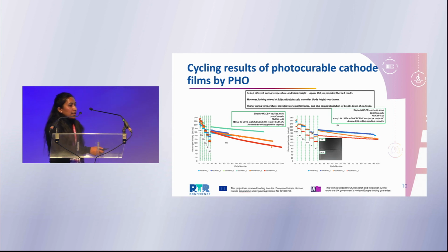So they are doing parallel testing of NMC with commercial NMC, to see if they can photocure it or not, and they have already tested with liquid electrolytes to make the validation, and further it will be tested on the solid-state electrolytes. Here the partners are focused on optimizing different temperatures and blade heights for the UV curable photopolymerizable cathode materials, and they have tested rate capability at different C rates, and they could achieve really good capacity, almost up to commercial electrodes, even after the photocuring and addition of different materials. So it's going in a good direction, I would say, compared to other NMC materials with other kinds of solid-state electrolytes. Given the challenges in this particular project, it's still going really well in terms of capacity and achieving most of the KPIs.